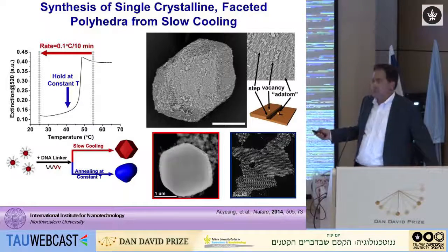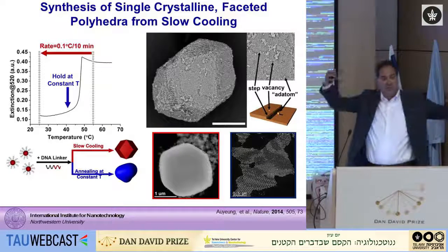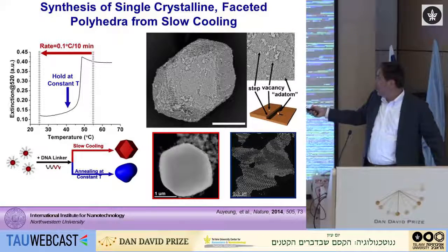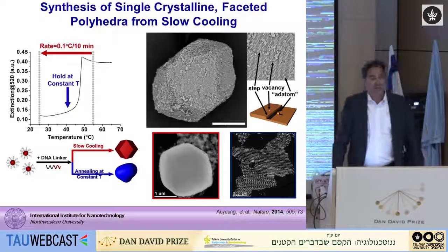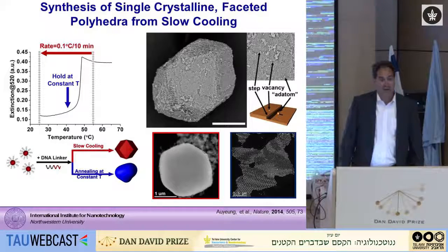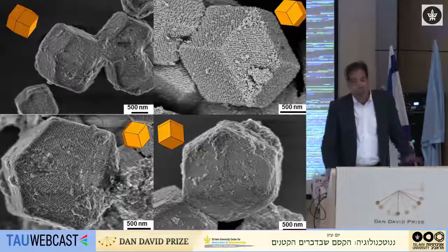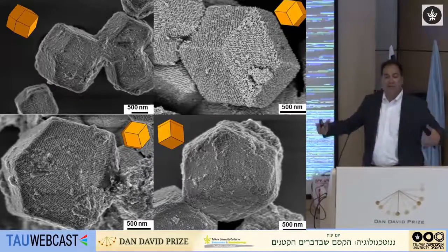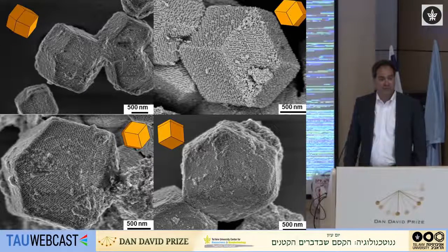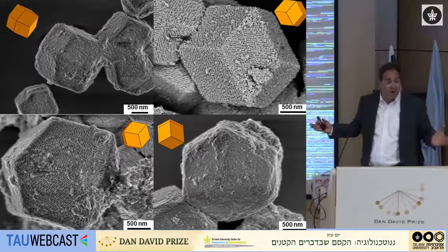We said the way organic chemists do this is they typically go to higher temperatures, supersaturate the solution, then slow cool and allow the system to nucleate. And so we built a modified PCR machine where we could control the temperature rate, a tenth of a degree every 10 minutes. If we take this system, remember all the particles are dispersed because you're above the melting temperature of the DNA, and now you cool through this, and out fall these beautiful rhombic dodecahedron crystals. And it happens every single time. It's an unbelievably reproducible type of controlled crystallization because you program the parameters.